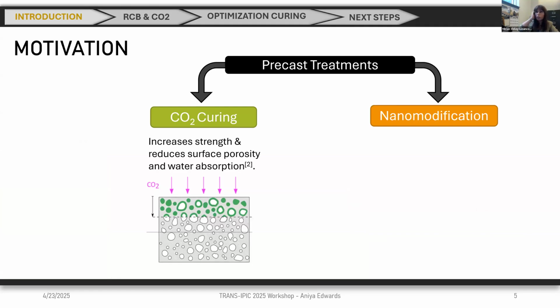One of the reasons why we were focusing on CO2 curing is because it is known that it increases the strength. That's something that we know, and it also reduces the surface porosity and the water absorption. When the CO2 starts to penetrate, it will start to carbonate the surface layer in particular. It's not going that deep, especially with CO2 curing, but in the surface layer it will reduce the porosity, and therefore we might have good effects in terms of reducing water penetration and so forth.